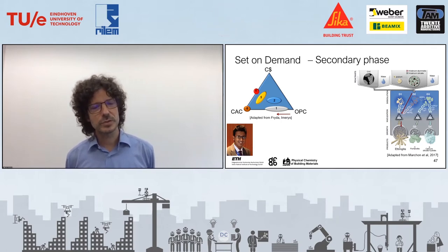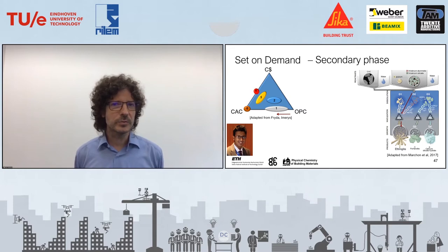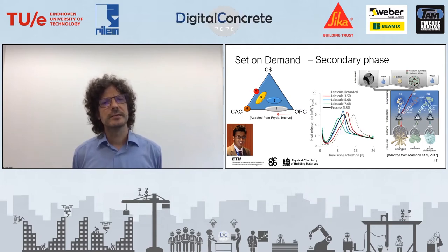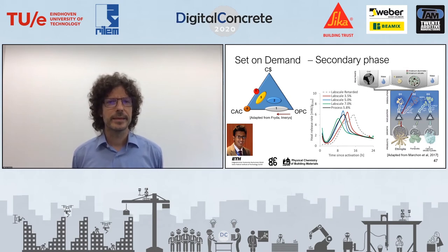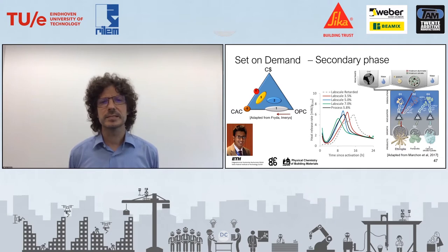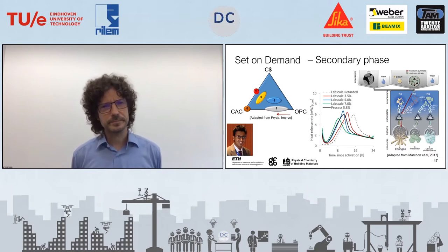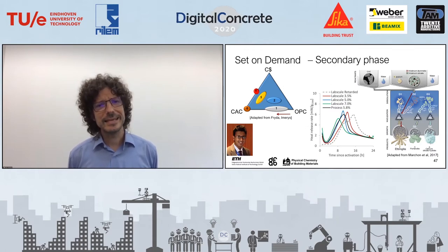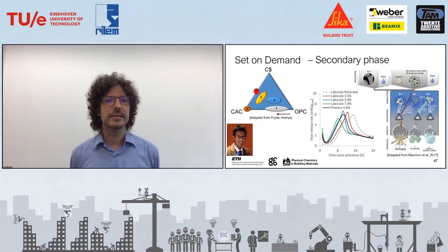This has various consequences. First, it creates solid volume, which is beneficial for the strength gain, but also it changes the kinetics of hydration. Now, you may notice in the center of the figure that the main hydration peak is somewhat changed, but more importantly, in the very first periods, we see an increase in the rate of heat release, which indicates that hydration is proceeding at a higher rate. And this is one of the keys to the process.